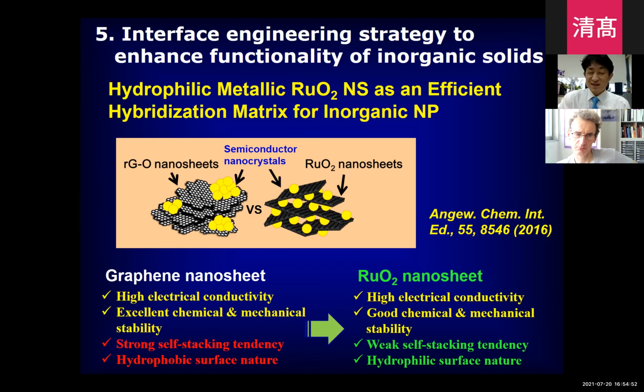To overcome such a drawback of graphene, we tried to replace graphene with a hydrophilic and metallic inorganic nanosheet like ruthenium oxide. Ruthenium oxide shows high electrical conductivity and good stability, but there's no pi electron, so it is free from strong self-stacking tendency. Also, it has polar chemical bonding, so it is good for getting strong electronic coupling and interfacial chemical interaction with many kinds of polar inorganic solids.